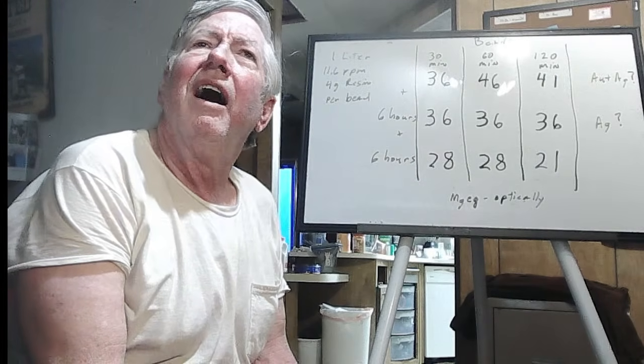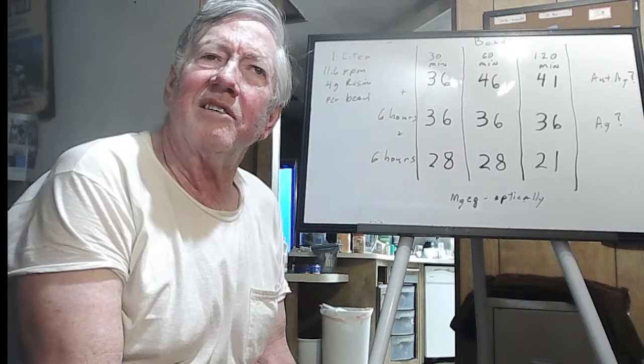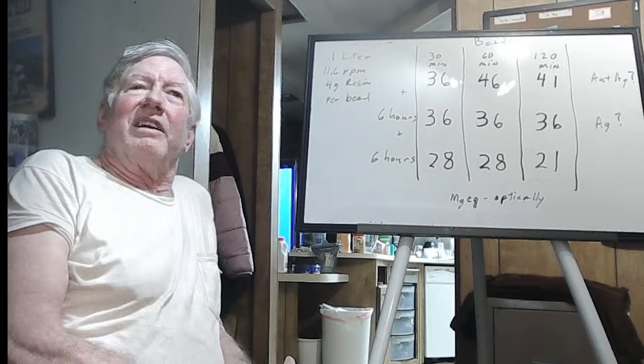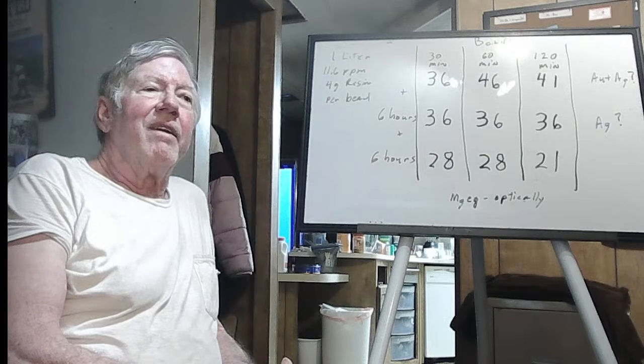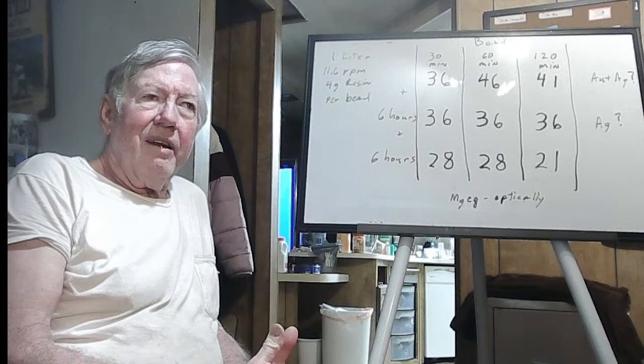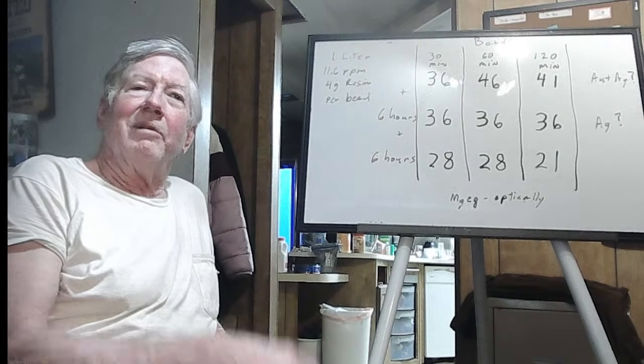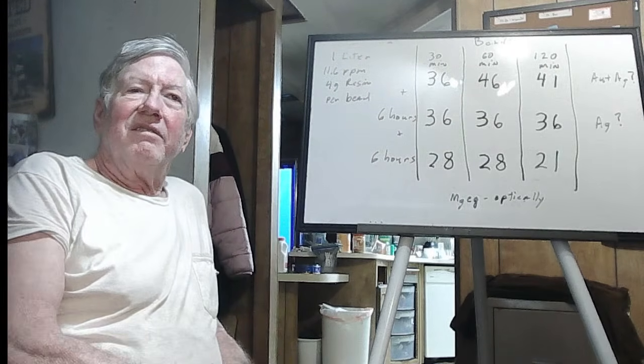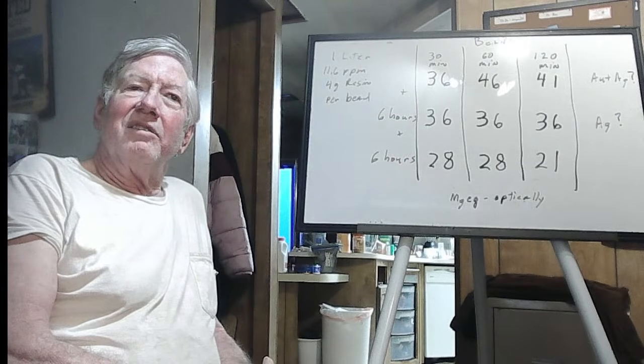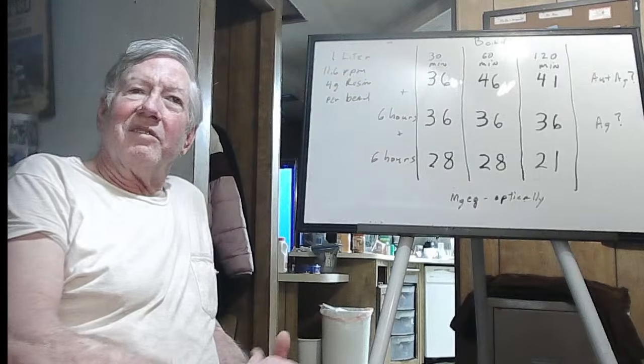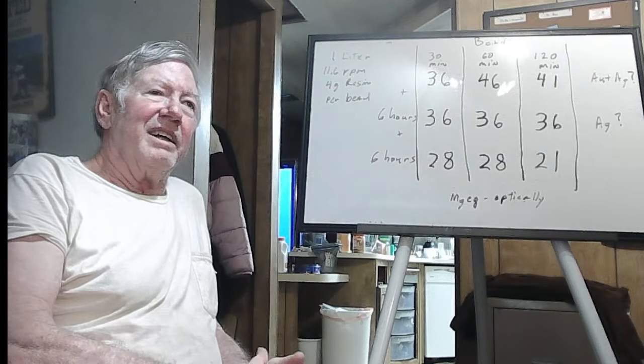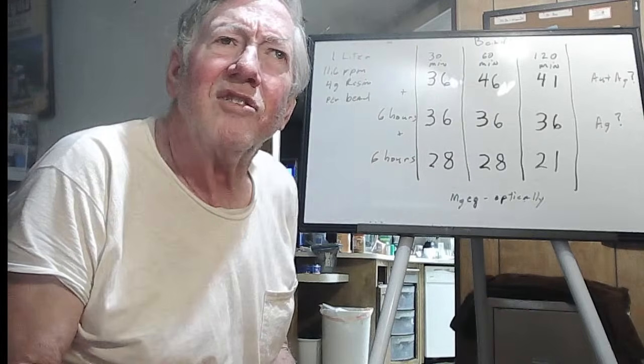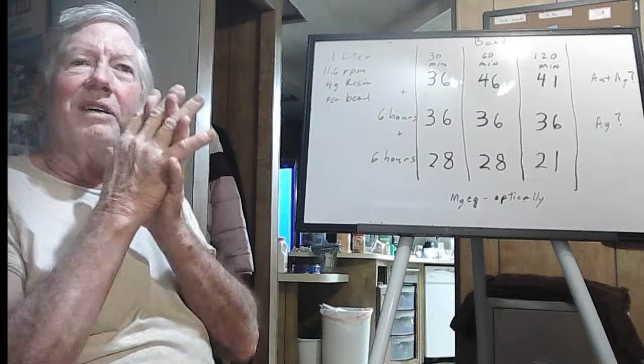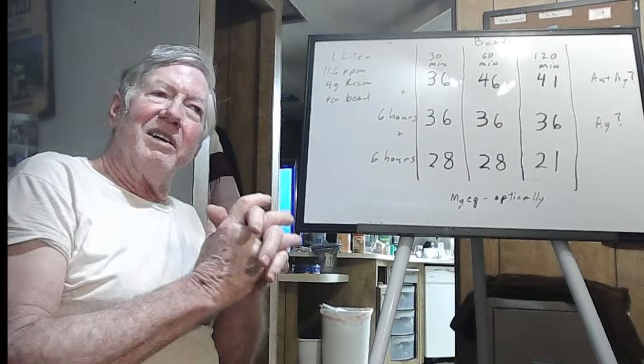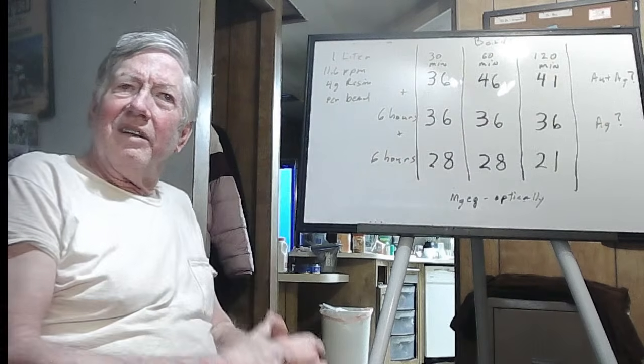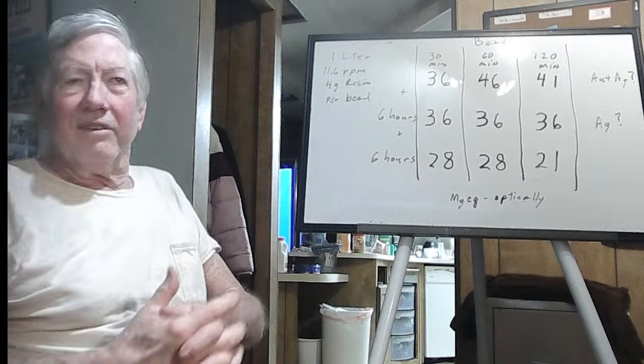Digested with the hydrogen peroxide. They were getting ready to load it in the ball mill. And then later today, they were going to get it out of the ball mill, put it into the cement mixer, add extra fluids to bring it up to the 3-to-1 solid liquid ratio, and then add the gold. So, really quickly, they're going to need to know how much resin and how long to roll it in order to get the gold out of the solution.